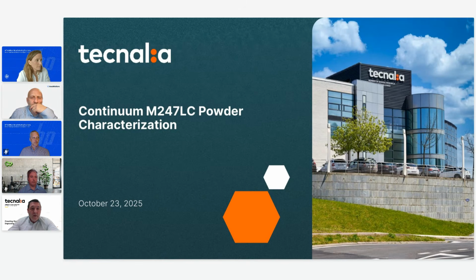We also take a look into the sintering activity of the powder, because we need to have a good balance between the flowing properties that we will also evaluate and the sintering activity of the powder. We need to have a good balance between how well the powder can be deposited into the printer and the final sintering activity of the powder. And together with that, as I said before, the evaluation of the rheological properties, the static flowing properties, as well as the dynamic flowing properties. So with that, we can have a very good picture of whether that powder is suitable for the binder jetting process. Of course, later on, we need to print it, then we need to sinter it, evaluate the mechanical properties, etc. But with that, at least we can have a first image of that.